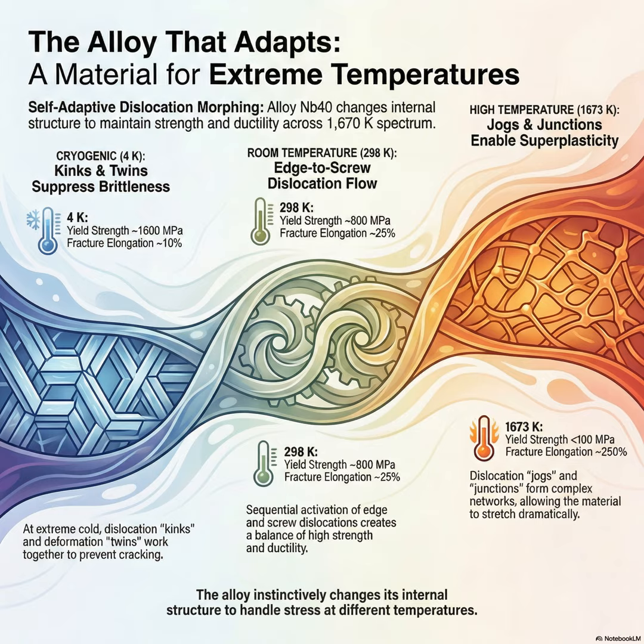Because these junctions rapidly connect to form these huge extended dislocation networks and subgrain boundaries. And the accumulation of all these networks drives a process called dynamic recrystallization. Dynamic recrystallization. That sounds like the material is rebuilding itself while it's being stretched. That is precisely what it's doing. The microstructure is constantly renewing itself, on the fly, releasing all the built-up stress.